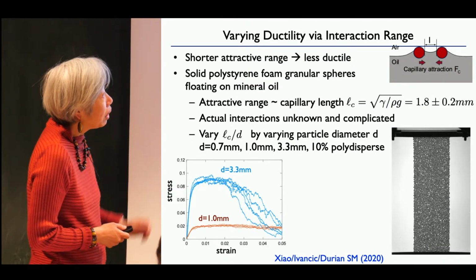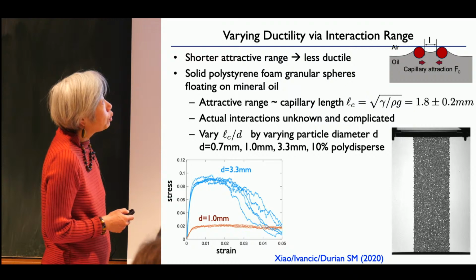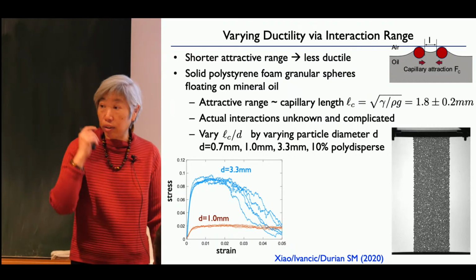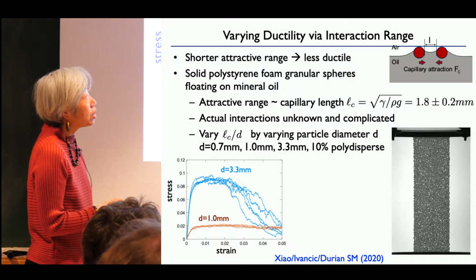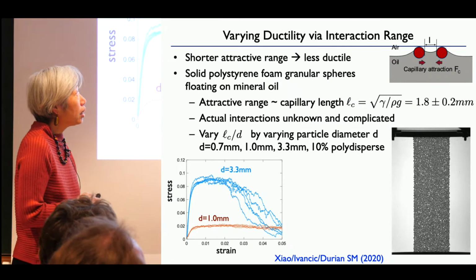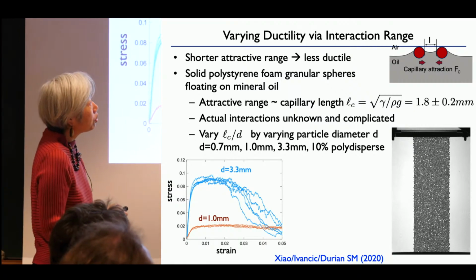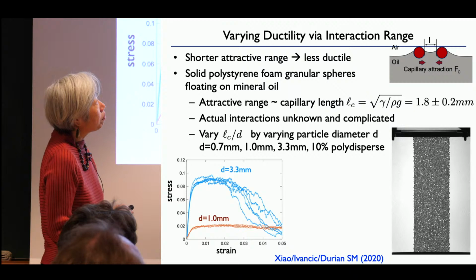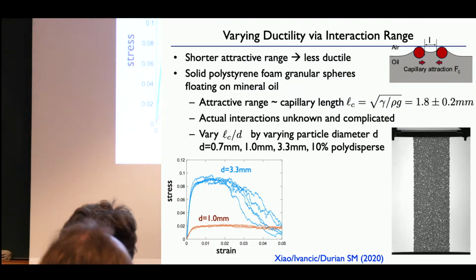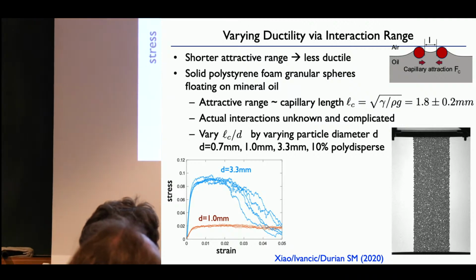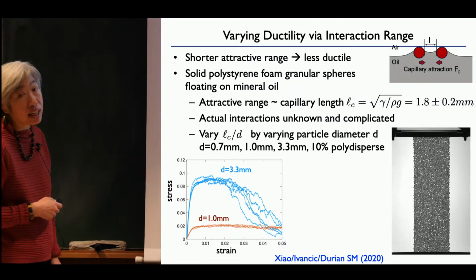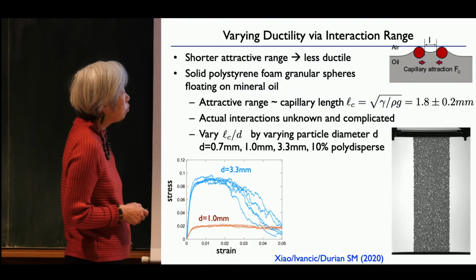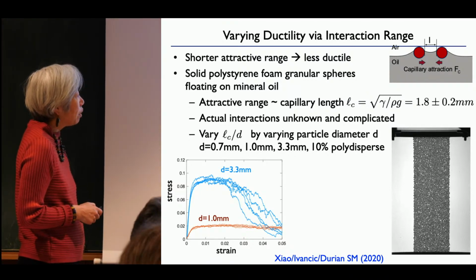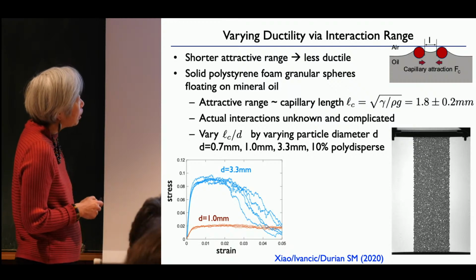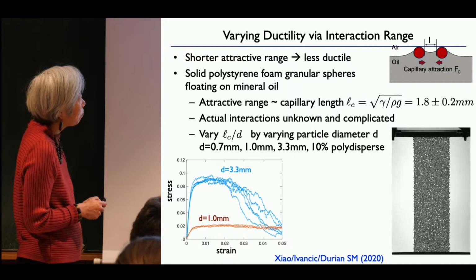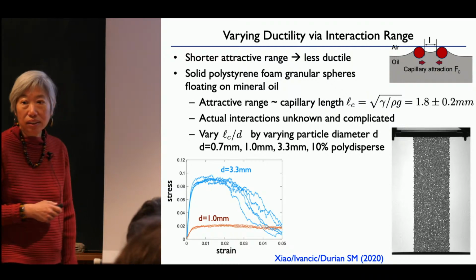This is work done by Doug Durian. So these are grains that are suspended at the interface of oil and air. So there's a capillary attraction that pulls them together, and then, of course, a hard-core repulsion. This capillary length is just set by the surface tension, density, and gravity, so that's fixed. But what they vary to vary the attractive range is the size of the particles. There are two sizes of particles, 1 millimeter and 3 millimeter. In the 1 millimeter case, you see typical ductile behavior. In the 3 millimeter case, each one has a small stress drop, not very big.